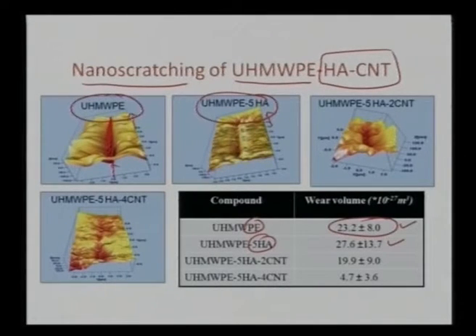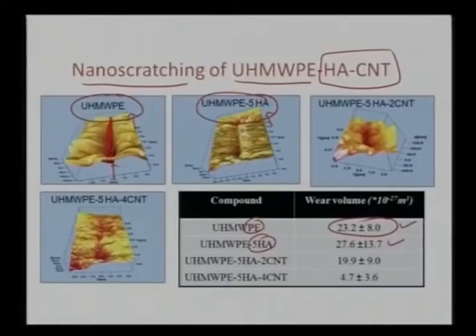That is much more contradictory, because once I am reinforcing my polyethylene with a certain ceramic, I would expect the wear volume to go down. But what is happening here is that the interface between hydroxyapatite and polyethylene may not be that good. So hydroxyapatite is probably loosening away, and that again is acting as a scratching media for the polyethylene. That is the reason I am seeing a much higher wear volume once I am reinforcing with hydroxyapatite. But once I start introducing some carbon nanotube, at 2 weight% and 4 weight%, I am seeing much reduction in the wear volume.